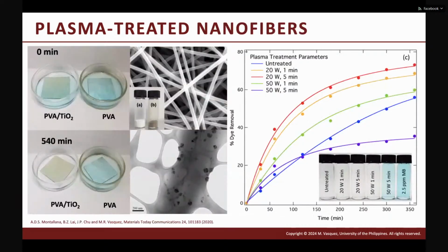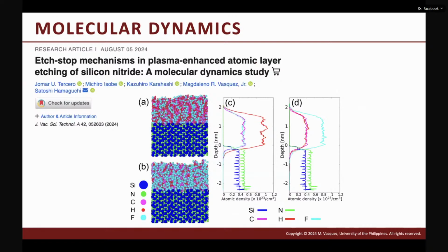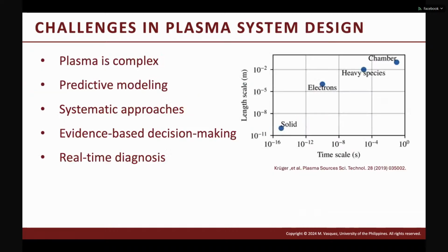So this one is the nanoparticles that I mentioned earlier. So we embed this in nanofibers and use this as a photocatalyst. And we can improve, using plasma treatment, the degradation of organic dyes. Okay, this one is a recent work. We also did some molecular dynamics study to determine the etch mechanism in plasma enhanced atomic layer etching of silicon nitride.